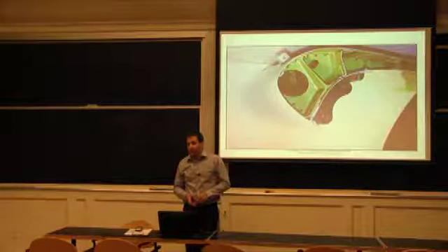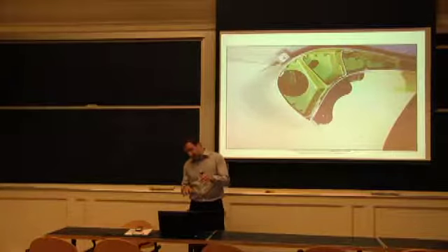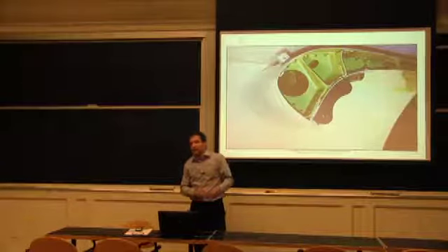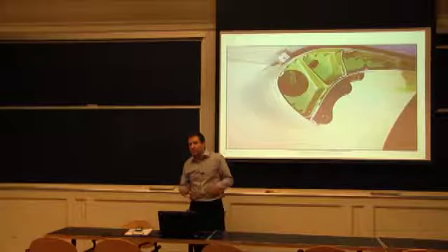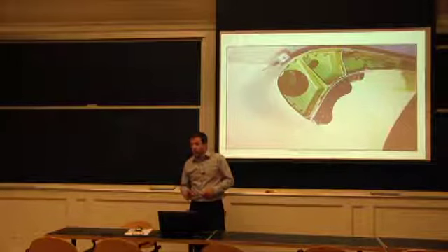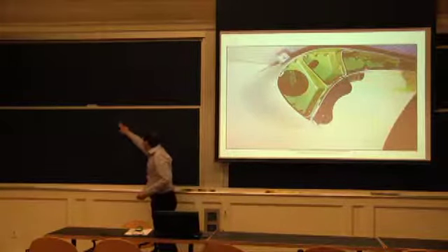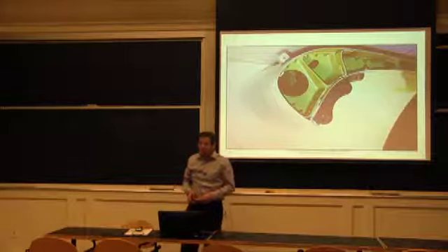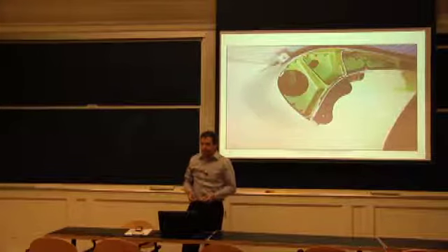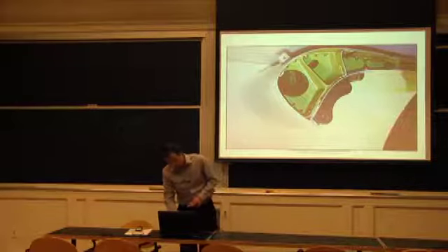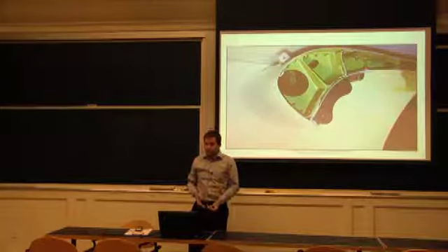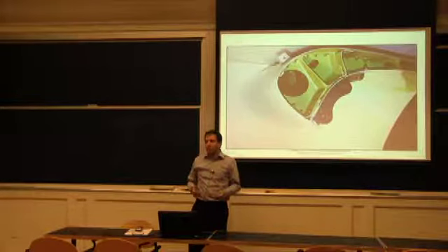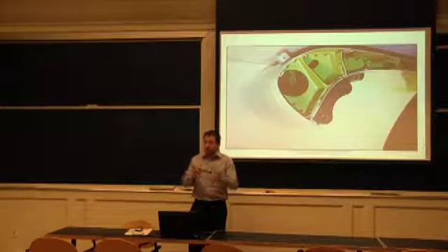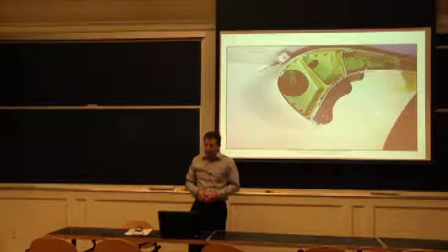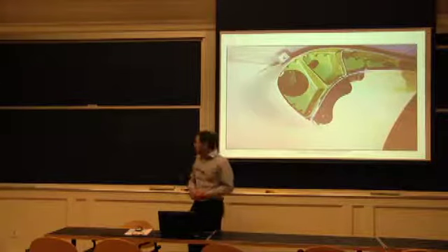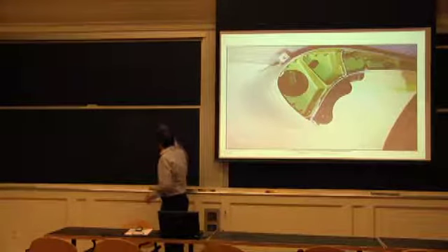And the good news, though, by engineering, when you look at this, there's clearly going to be a side in tension and a side in compression. And the web, we can put holes in it, and it's still fine. So if you have a little impurity in the mold, it's okay. So you had essentially to verify that your top flange was going to have the properties you required. Having a little impurity on the compression side will not affect the buckling capacity, which is a controlling factor here. And same for the web. So there was only a small portion that really had to be 100% detail inspected to look for anomalies from the casting. And that was the way to get away from the casting factor of safety.